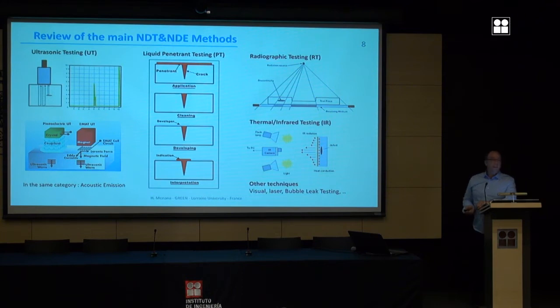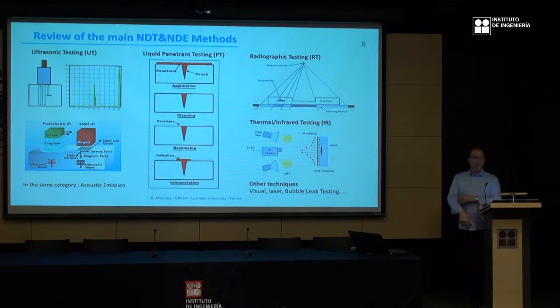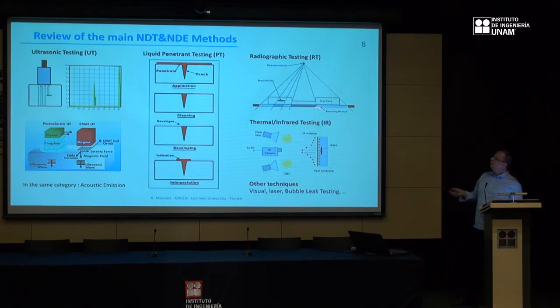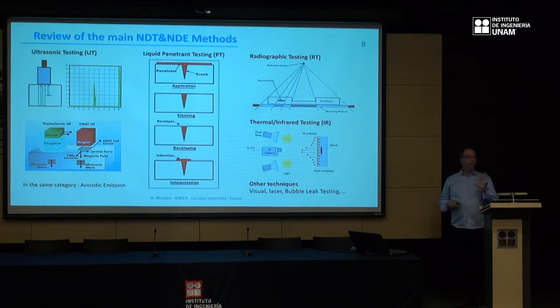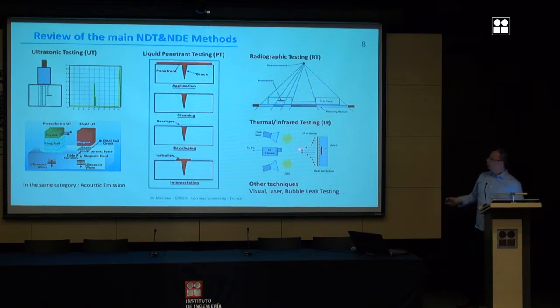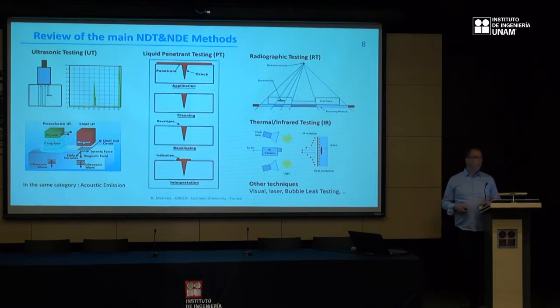We have radiographic testing. It's like the radio we use in medicine for bone imaging. We put a tested material between X-rays and a developer, and then we can detect an eventual flaw in the material. Thermal infrared testing: we heat the surface of a material, and then with an infrared camera, we can detect the presence of a flaw, since the thermal properties change with the presence of a flaw in the tested material.